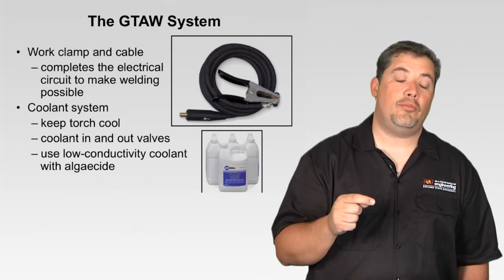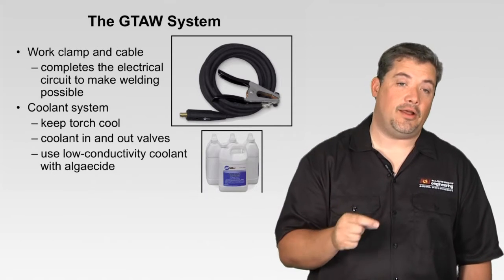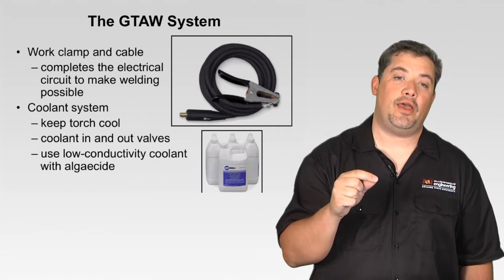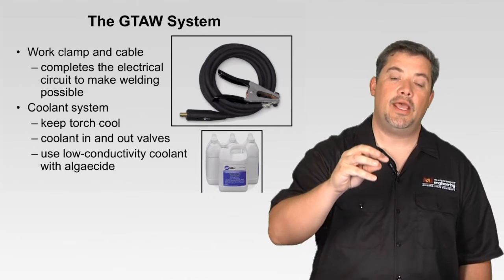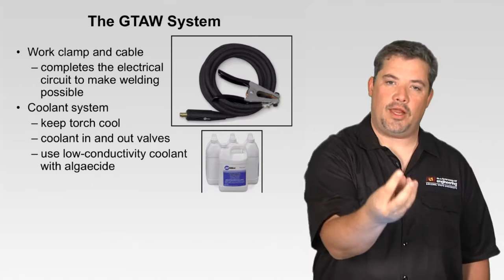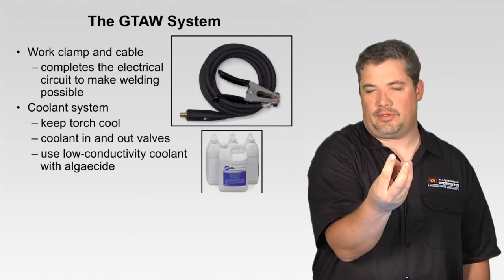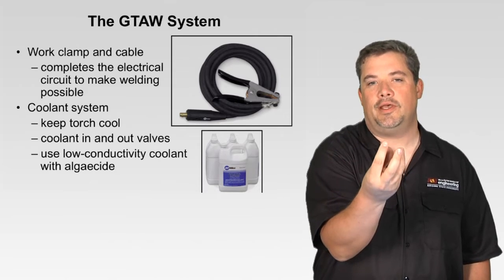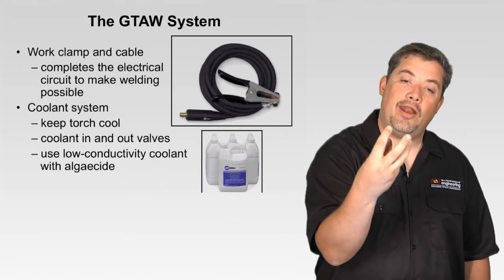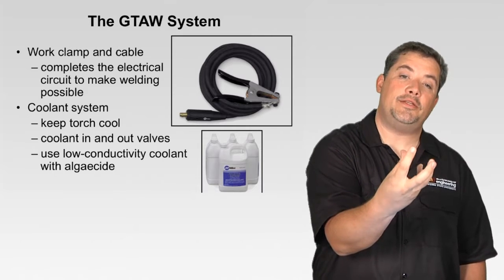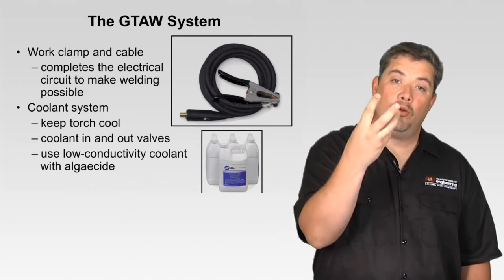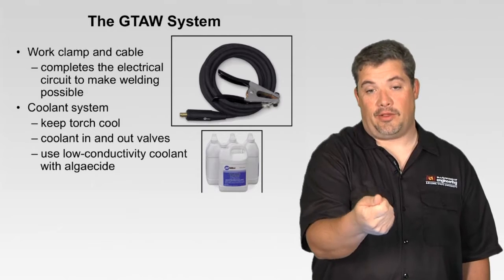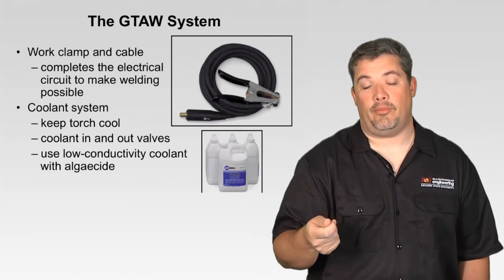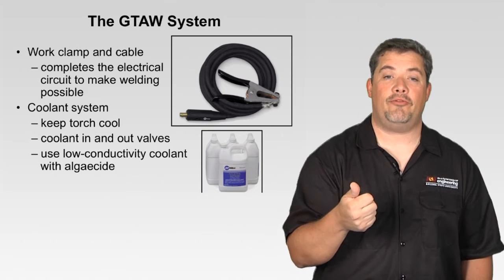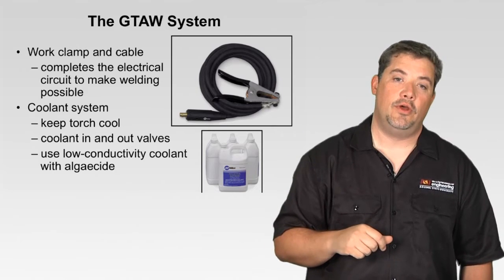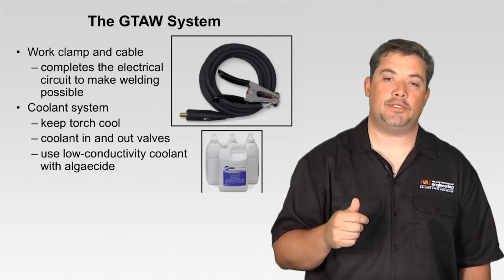People will use automotive antifreeze. That's suicide on a coolant system because automotive antifreeze has clogging agents in it, and those clogging agents go to the head of the torch, and up in those little tiny areas in the head of the torch, it'll see that as a leak, and it'll start to build up those clogging agents in there, and now we have a destroyed torch. It's not getting cool. I'm out $300, $400, $500 for a new torch. So automotive antifreeze, horrible thing to use in a TIG welding coolant system.